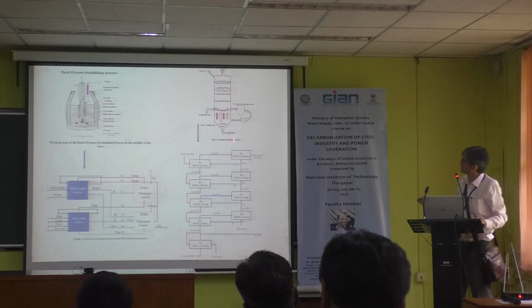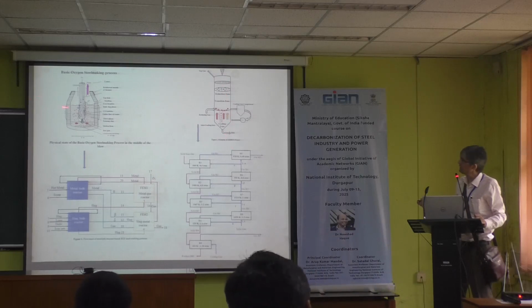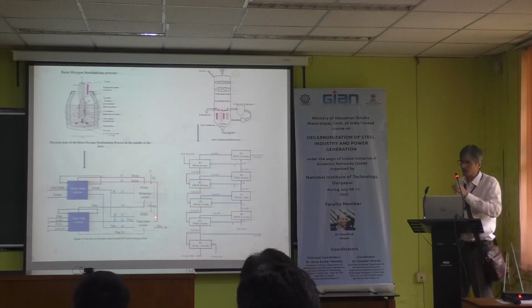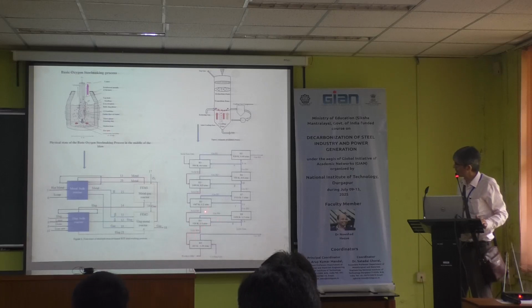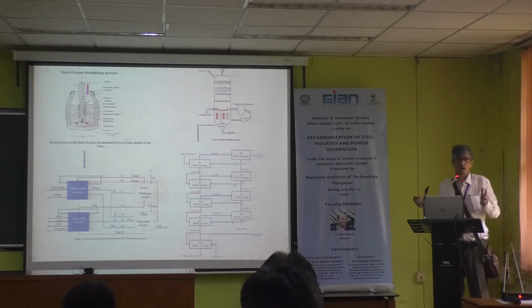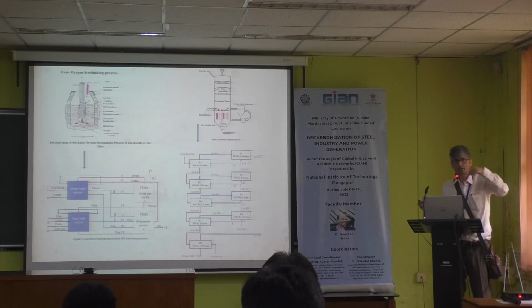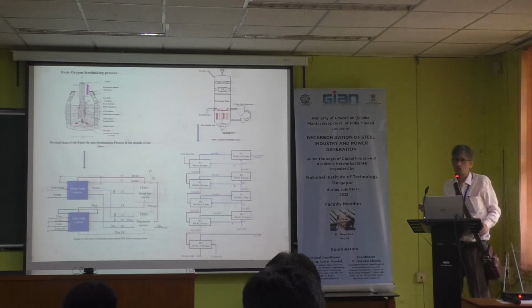And this is the reactor, for example, of any kind of shaft furnace. Here we have predominantly gas solid reaction, and here we have the slag metal reaction or gas solid reaction. For gas solid reaction, we adopt a similar approach, but we apply another kind of system where there is an interaction between the rising gas and the descending burden. But not all of the gas reacts with the burden. A part of it is bypassed because of the kinetic limitation assisted by diffusion in the solid, and accordingly we have mathematically translated it.